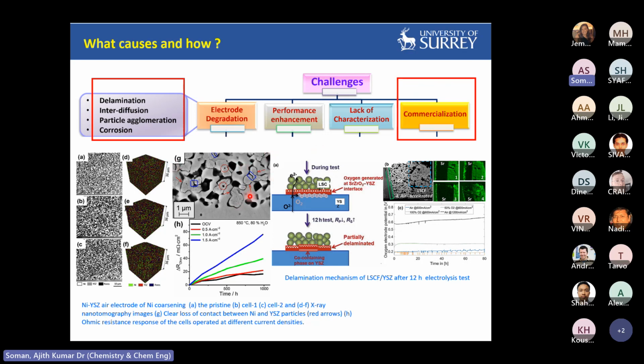And this is how the previous report says that once it has a degradation, you will lose the contact points between the nickel oxide GDC and the current collector, so it is a serious issue. And the interdiffusion again is an important issue, so we need to be very careful about the interdiffusion between the anode and the electrolyte, because the strontium species tend to react with the LSCF. It produces the insulating strontium zirconate phase. It is absolutely a resistive layer, so it will lower the performance. So the combination of all these things will hinder the commercialization of this particular technique.